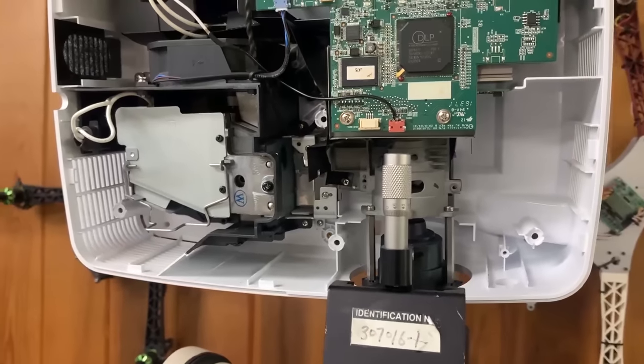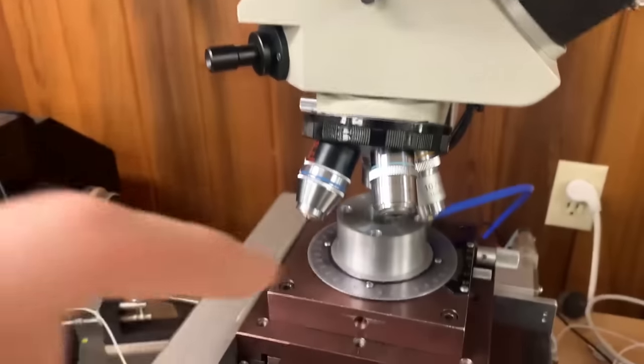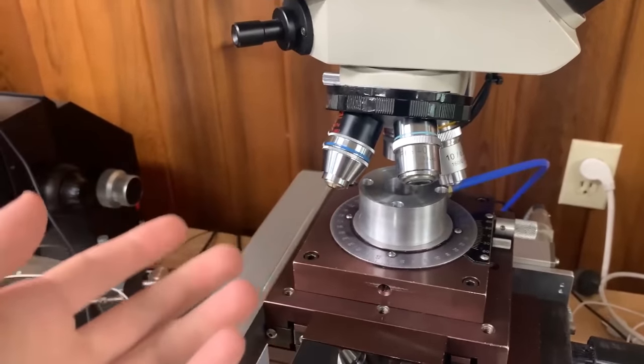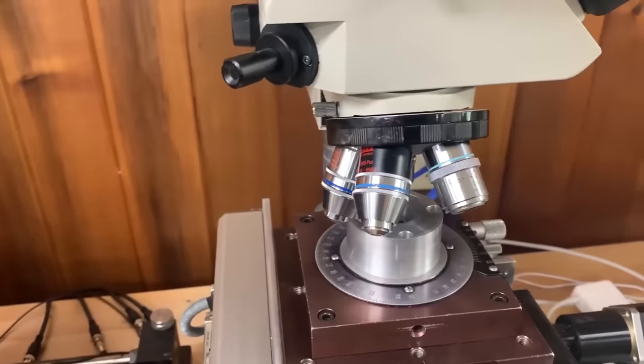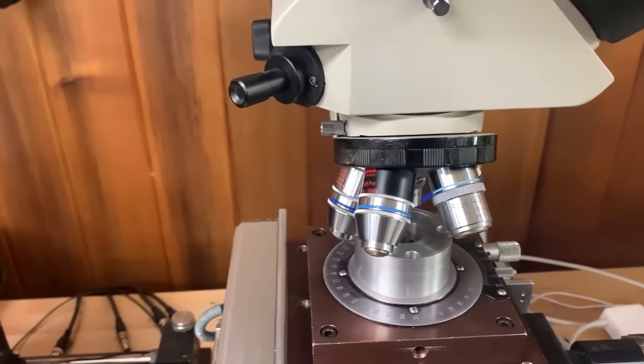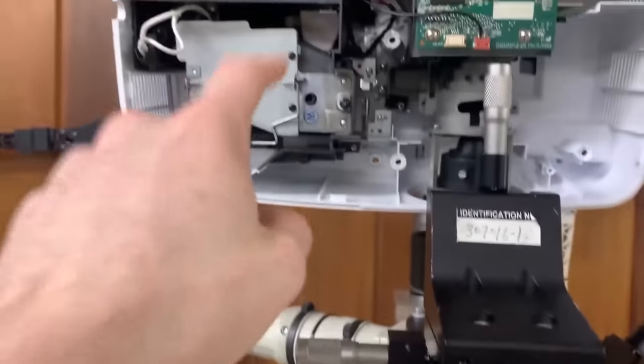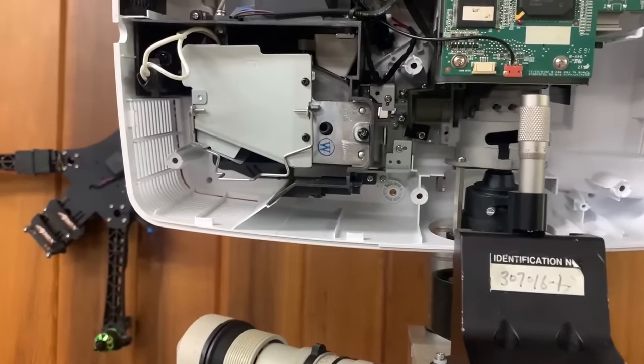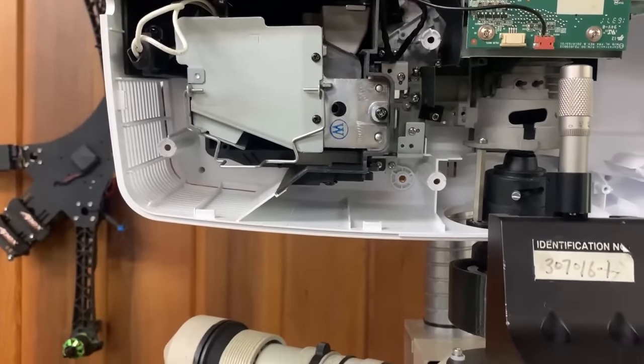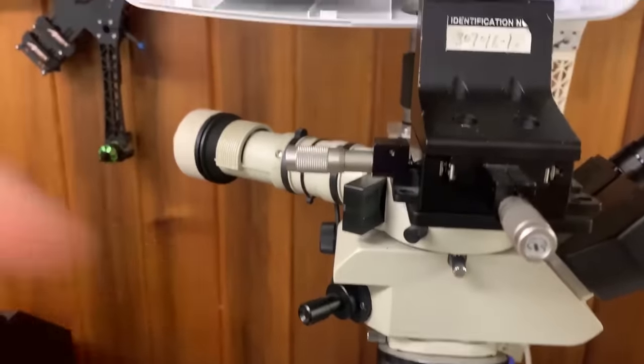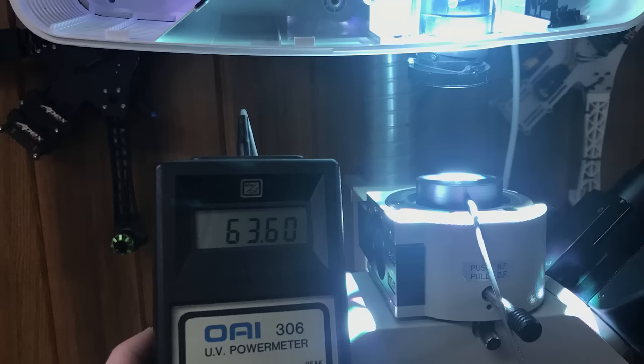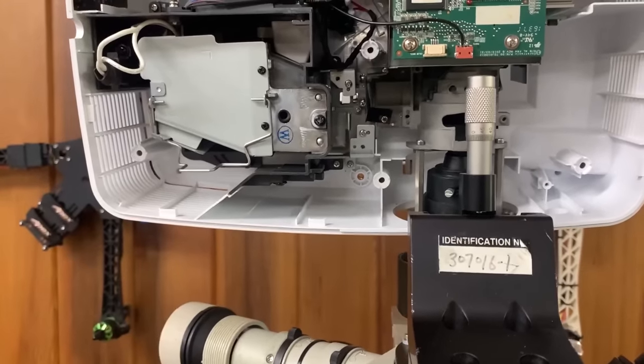After that, you can start to estimate the exposure time that it'll take to expose a wafer. Normally, photoresists have a dosage of about 100 to 200 millijoules per square centimeter. The intensity of a UV lamp is rated with units of milliwatts per square centimeter. If you cross out all of your units and divide those numbers, you're left with only seconds, and that number tells you the required exposure to get the expected dose.